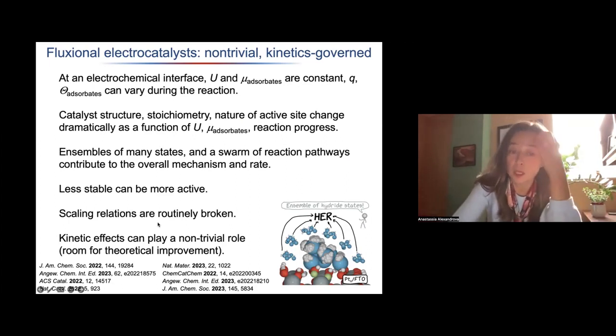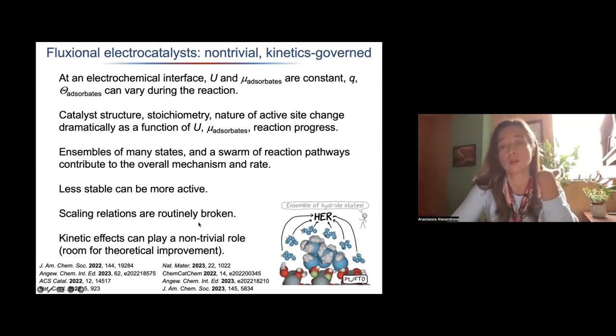Less stable can be more active. I didn't show you this, but we break scaling relations. So if you're from the catalysis community, this is some sort of holy grail there. Scaling relations break when you change structure very much. And also, in some cases, we really have to watch out for kinetic effects that break our convenient Boltzmann paradigm.